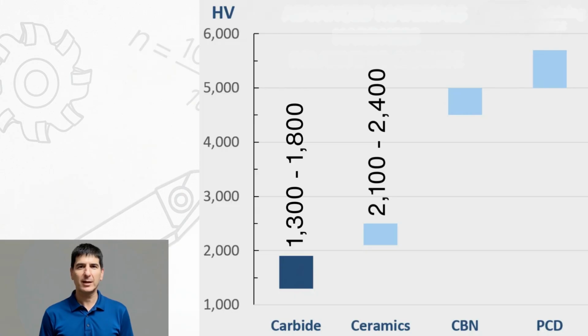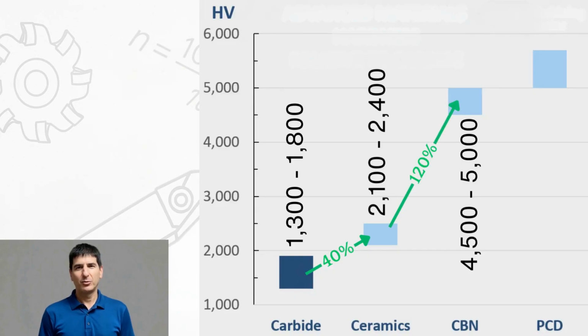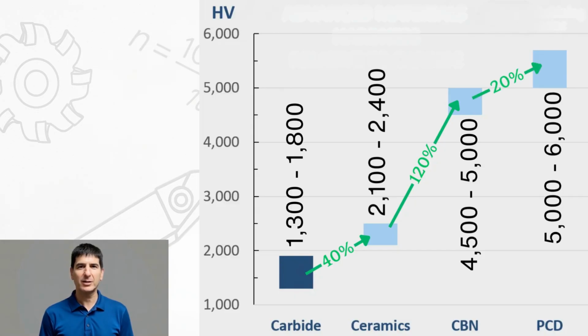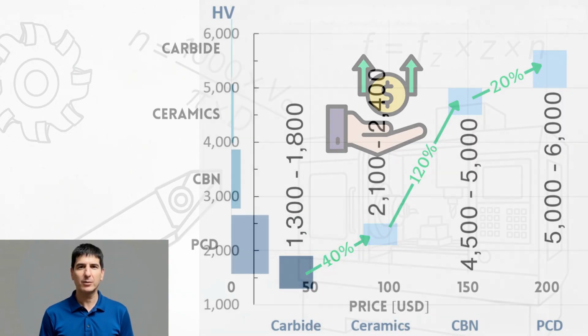Carbide sits at 1300 to 1800 HV, ceramics jump up to 2100 to 2400, that's about 40% harder than carbide. CBN takes it further, reaching 4500 to 5000. And PCD inserts are the top at 5 to 6000, making them the hardest cutting material available.